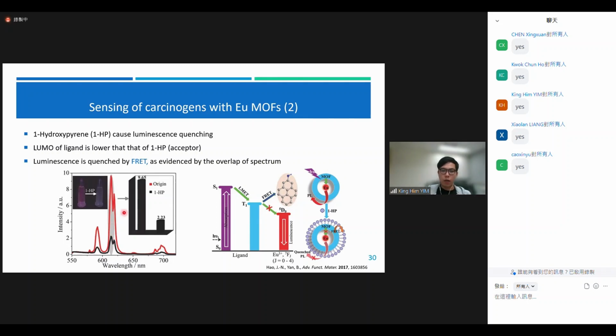And this can be attributed to the quenching by 1-HP. They try to investigate the mechanism by doing DFT calculation, and they confirm that the quenching of this Eu MOF is not by PET, it's by FRET. That means the energy will transfer to the 1-HP via FRET, quenching the energy transfer from the ligand triplet state to the Eu excited state.